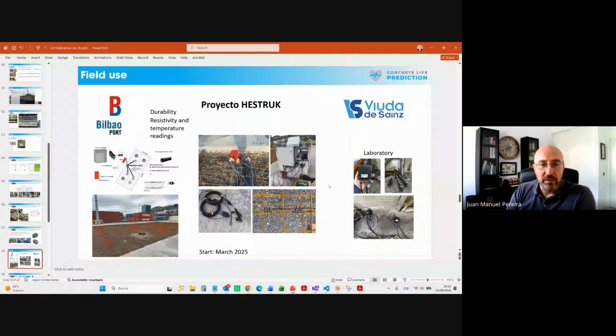Okay. This is a nice project, again, with the Port Authority in Bilbao, a different city. And this is with recycled aggregates. We did a 400 square meter test for a slab in the port with different types of replacement of recycled aggregates. So one panel is normal concrete, another one is a 20% replacement of the coarse aggregate with recycled aggregates, and the other two had a higher proportion of recycled aggregates, even going to 100% of the coarse and 25% of the sand with recycled sand, okay, which is a very big step up towards reducing the carbon footprint.